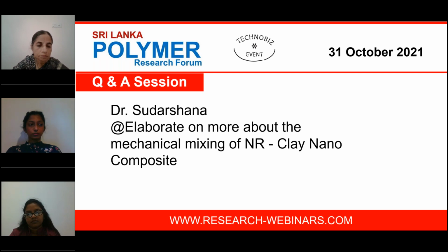But our advantage is that we can separate the clay layers into single or double or a few clay layers. That means we can minimize the clay layers, so later separating clay layers by friction is not needed that much. But if you add clay as a stack with a lot of clay layers directly to the rubber and do normal rubber processing, it is very difficult to separate the clay layers to a minimum. That is what I normally do.